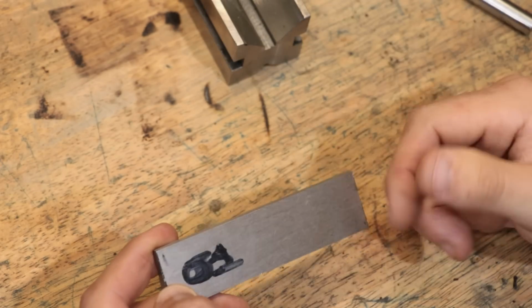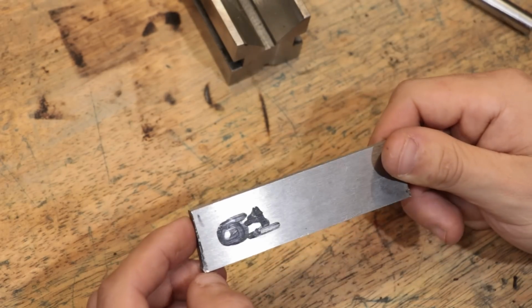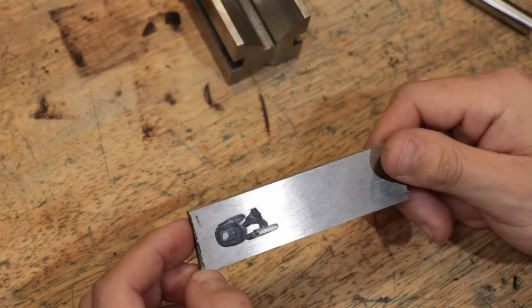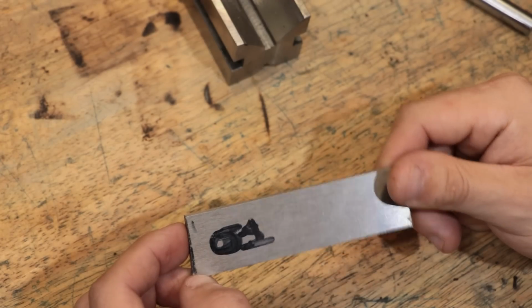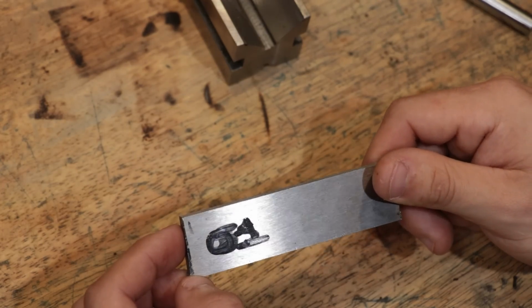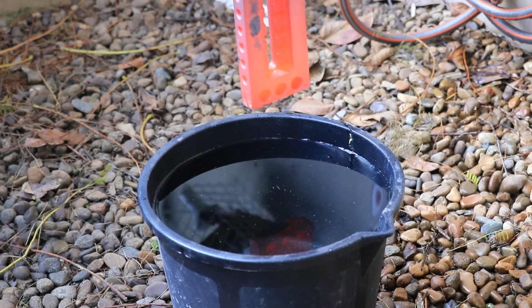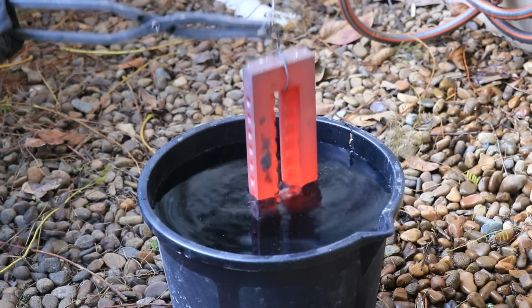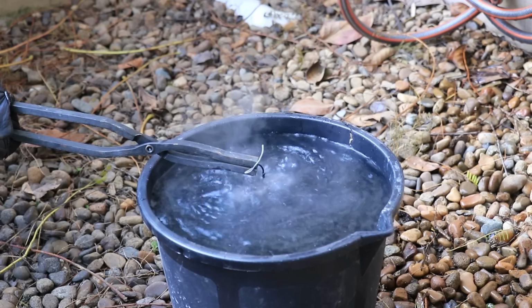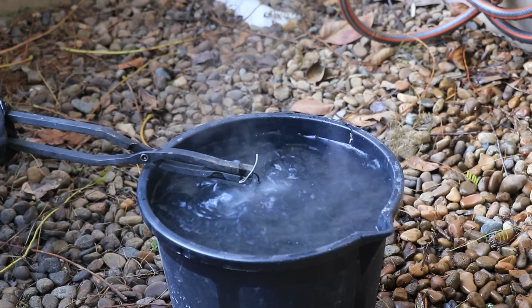Now, this range of time that we have to cool it down is known as hardenability, or at least it is related to it, and it has nothing to do with the total hardness that we can get. High carbon steel, for example, whilst it can get very hard, has very poor hardenability because we need to cool it down very fast to form martensite.